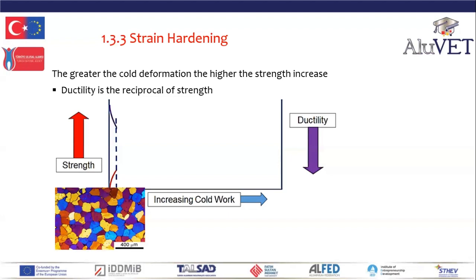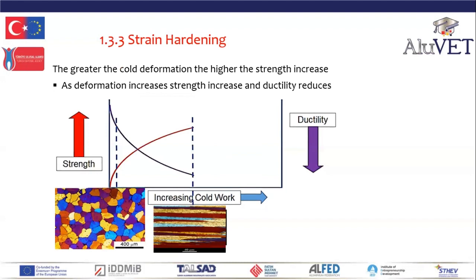Now in the graph, you can see we are plotting strength on the left-hand vertical axis and ductility on the right-hand axis. And in this picture, we see the annealed grains where their strength is low, the red line, and their ductility is high. As the degree of cold work increases, the deformation of the grains increases, so the strength increases and the ductility reduces.